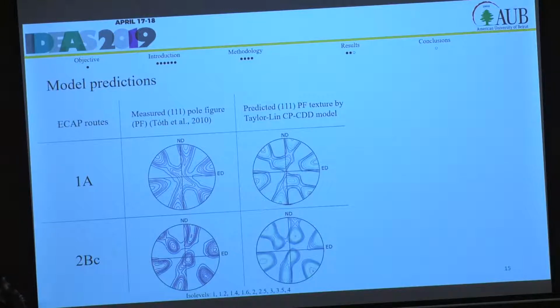Okay, some of the model predictions is the texture, which is one of the most important features after ECAP. So we have a very good agreement between the experiments and our model. These are the experiments and these are our model for 2 passes. And here we have a small video that represents the evolution of the texture with deformation. And as I mentioned, this texture represents the orientation of the crystals within the polycrystal.